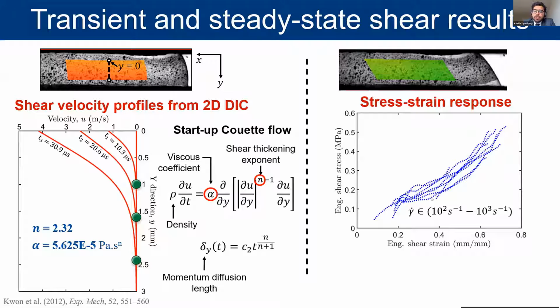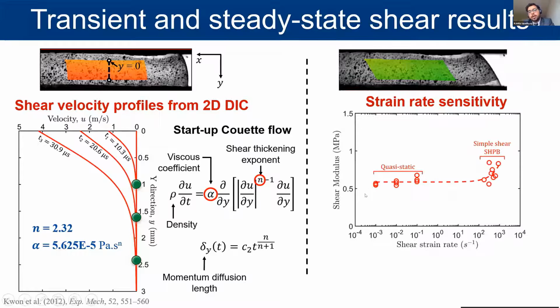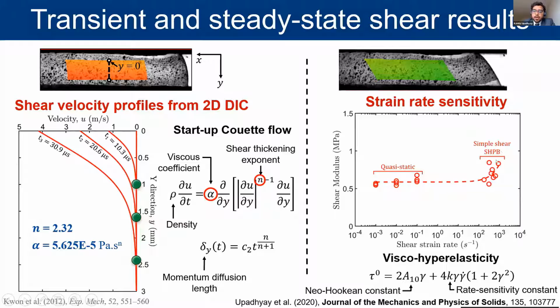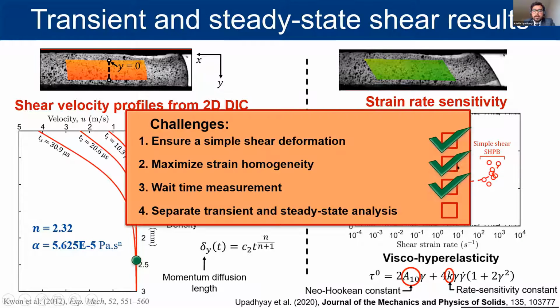If we analyze the modulus from these plots, we can get the modulus versus strain rate plot, which shows a weak strain rate sensitivity between the quasi-static experiments that we conducted and the simple shear experiment that we conducted using our dynamic test. This type of strain rate sensitivity can be modeled using a viscohyperelastic stress strain relation, such as this one that I recently proposed in one of my papers, which has two model constants. For PDMS, I obtained this as the Neo-Hookean model parameter and this as my rate sensitivity constant. And with this, I overcome the fourth challenge as well.